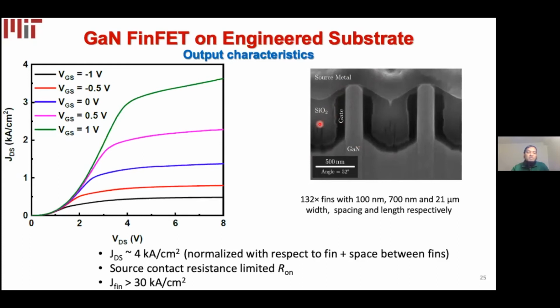And here we're showing the typical output characteristics of our GaN silicon FinFET fabricated on engineered substrate. We are reporting a current density of around 4 kiloamps per centimeter squared if we normalize the current with respect to the fin and the spacing in between the fins. However, our current devices are limited by the source contact resistance, which we will need to improve by applying a few techniques in future. If we consider the total current density flowing through each fin, it's actually very high. It's more than 30 kiloamps per centimeter squared.